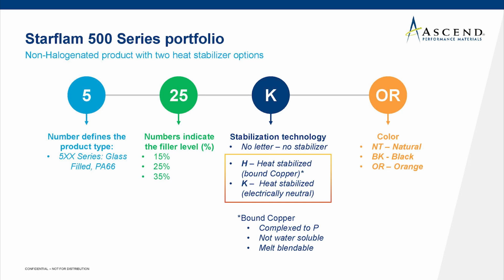And then we have two heat stabilizer options. There's a K heat stabilizer, which is electrically neutral, and then also an H heat stabilizer, which is represented by a bound copper system. And normally you would not want to have a freely dissociating copper material in electrical connectors, but in this case, it's a specialized material that is complexed to phosphorus, and it does not easily dissociate.